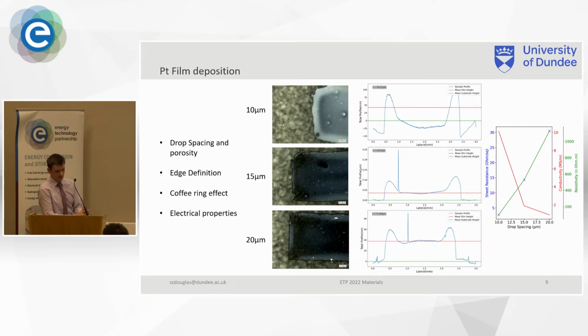and the electrical properties. What I found interesting was the thickness at the center of the films stays the same depending on the drop spacing, even though it's depositing more solution, more ink, so you'd think that might have an effect. Turns out it doesn't really have much effect, but it does seem to have an effect on the size of the coffee rings, as with the smaller drop spacing, the ink seems to move to the outside, so we get these coffee rings, which keeps the center at the same thickness. And you can also see the effect on the electrical properties, where we can go very dense and get very high conductivity, very low resistivity, and then we can increase the porosity and get lower conductivity as well, which is cool.